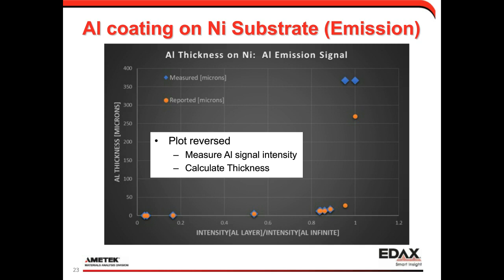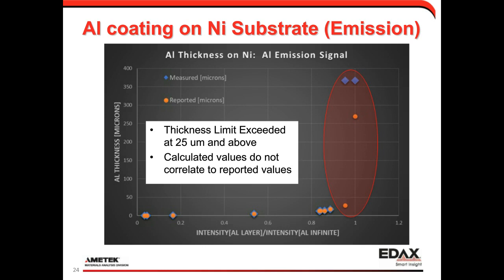So what you see here in the first place, when you're looking on the far end, near where the results are going to asymptote near a value of 1, our measured results are coming out in the hundreds of microns. Our reported values are in the range of 25 microns to 250 microns. I specifically picked foils that were thicker so I could see where the maximum thickness range for these types of measurements are. So you can see kind of what happens there. Our reported, or should I say our measured results don't correlate with our input reported values. And that's because we're in a region where the layer is too thick at this particular point.